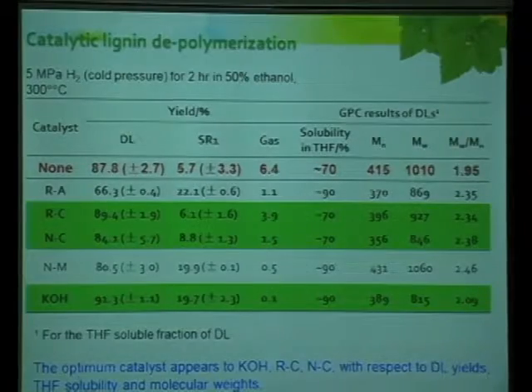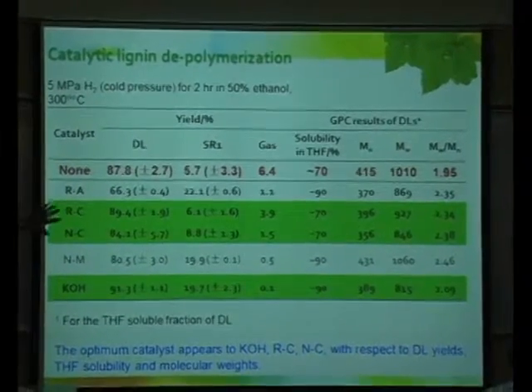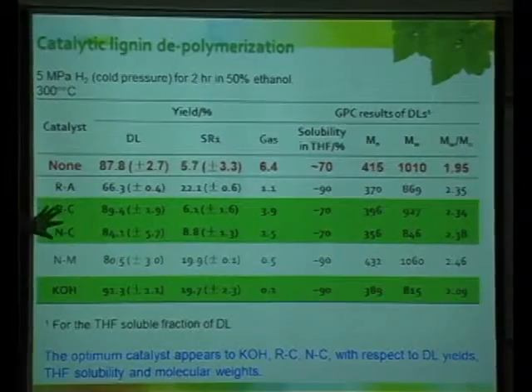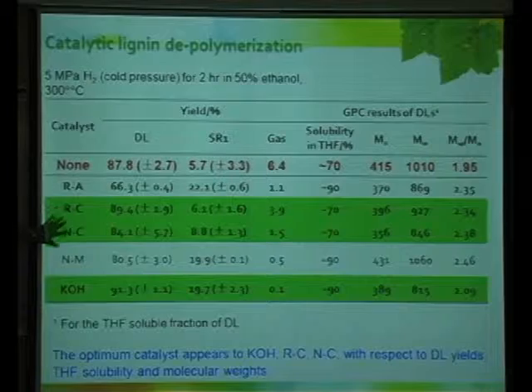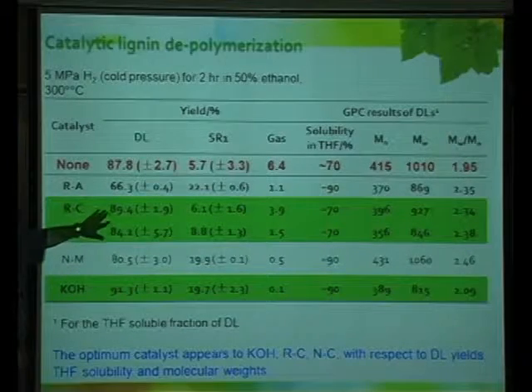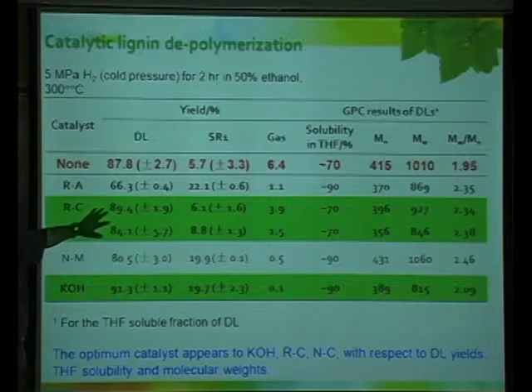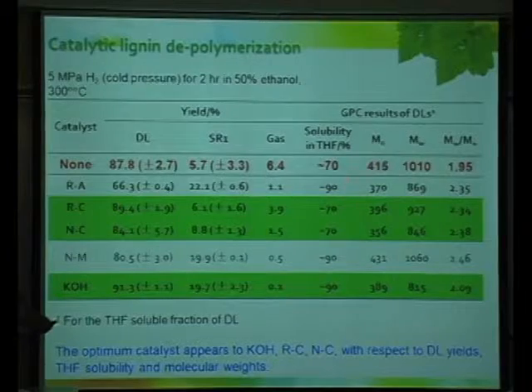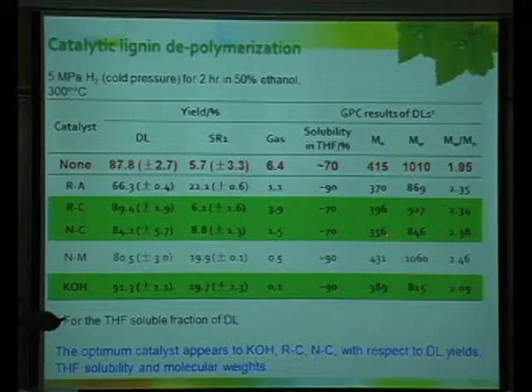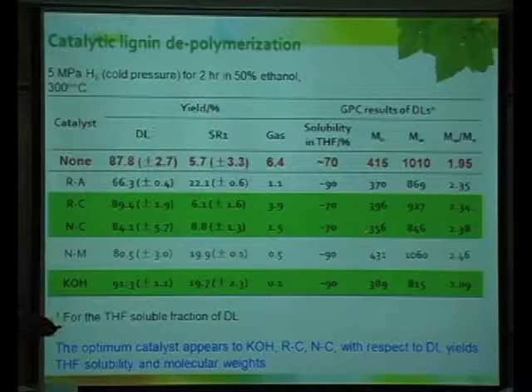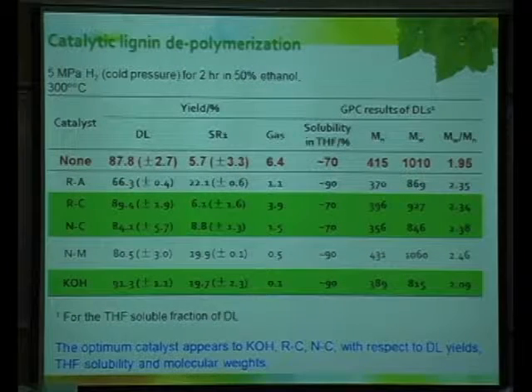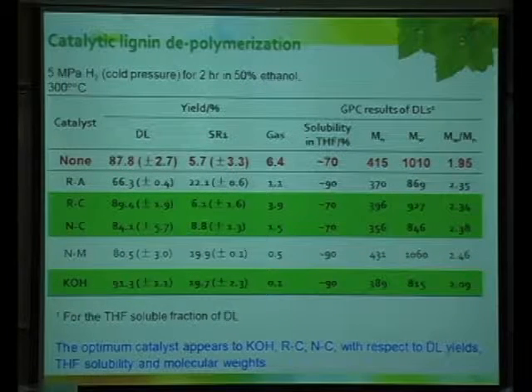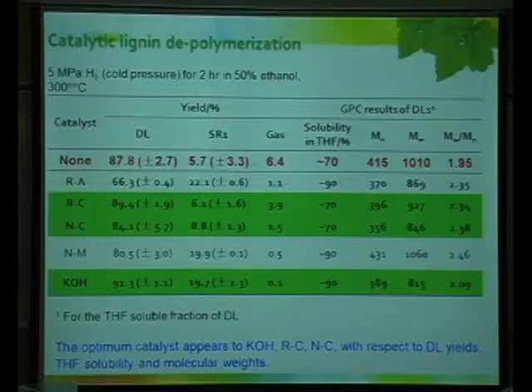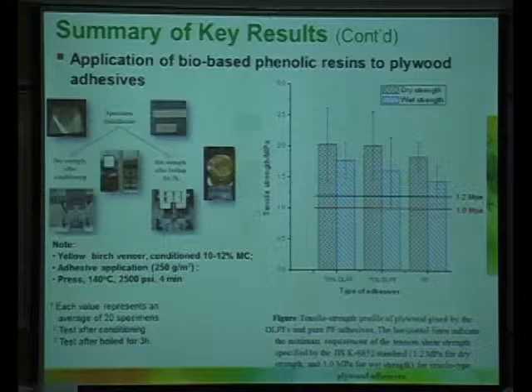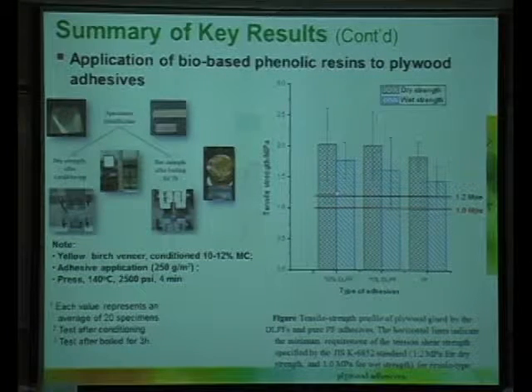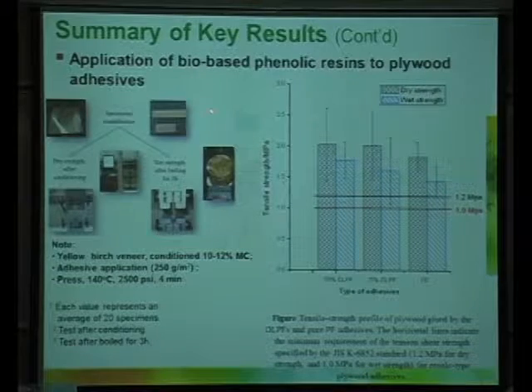And then we try some catalysts in the system, and some catalysts are shown here. For example, we try different catalysts. Some catalysts can slightly change the yield, but not significantly. But the catalysts can reduce the molecular weight further to 400 to 350. So those are the effects of catalysts. Catalysts can further decrease the molecular weight. And then application. So for engineering, we look at the application. How the biophenol can be utilized.